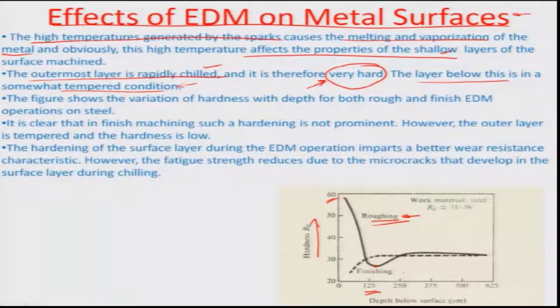This could actually be a result of the fact that adjoining the rapid chilled layer is a layer which is also supplying the amount of carbon which could really lead to a martensitic state formation on the top layer. So, this is a kind of buffer layer, you could say, a carbon provider for martensite to get generated on the top layer. And then obviously, as you go further, these layers are more or less in a tempered condition, the hardness just gradually changes, until it reaches almost a stability of near about 30 to 32 Rockwell hardness.